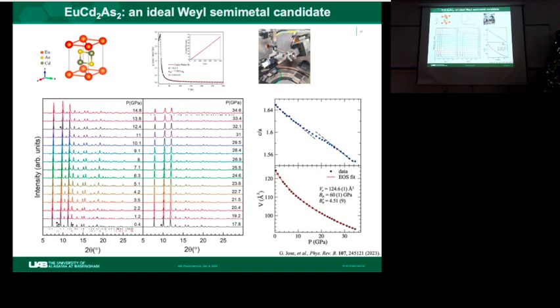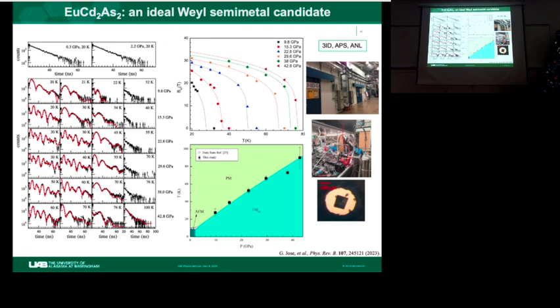So here, c/a typically suggests some sort of electronic transition there. And then we said, okay, it's great, the crystal symmetry is maintained, and how about the magnetism? Is the magnetic configuration really tuned into an out-of-plane ferromagnetism? So we took the sample in the diamond anvil cell to the synchrotron beam and used synchrotron-based Mossbauer spectroscopy on europium-151, and then we